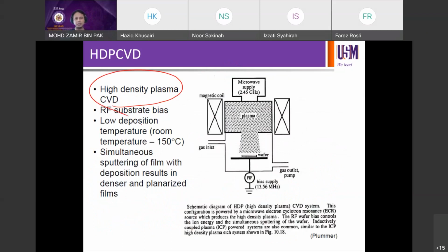Plasma also, but this one is high density. To be able to have this kind of plasma, you need to use a microwave supply, 2.4 gigahertz, to generate high density plasma. The rest are pretty much the same. So high density plasma, microwave supply. You have RF supply as well, just like the way we run RF sputtering, 13.56 megahertz. That will require your LC network, like an RF system. But the rest are the same: chamber, electrodes, inlet. With high density plasma, you may also introduce bias.